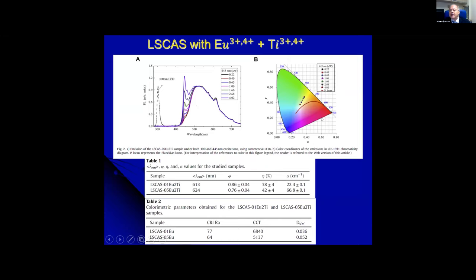And then in this glass, we measured the quantum efficiency with a thermal technique. All the time we make this glass, we make characterization. We use conventional luminescence techniques and also photothermal techniques because we evaluate the quantum efficiency of the material. It's very important for the application to have a very efficient material in terms of luminescence. In this case, we measured a quantum efficiency of around 40%, and also the CCT temperature and the color rendering index we get in this glass are inside what is predicted by the Japanese norm of regulation of illumination quality.